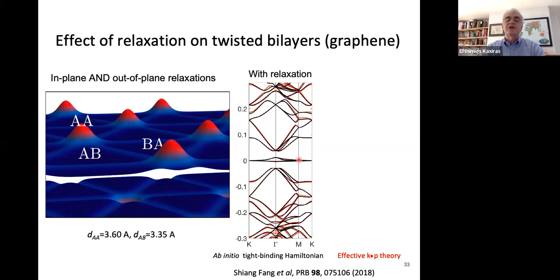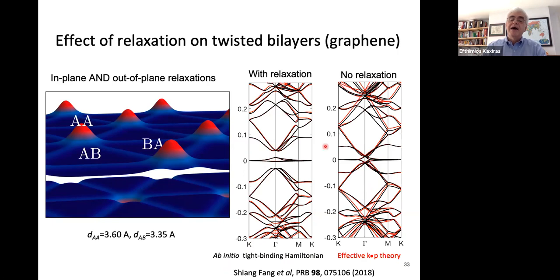So here's the band structure again, and here are the bands associated with this relaxed atomic configuration. The black lines are from our ab initio tight-binding Hamiltonians. The red lines are an effective perturbation theory, which basically captures all the important features. So this is with full relaxation, and it's very realistic, corresponding to the experimental measurements. Without the relaxation, the bands are actually a bit of a mess. No gaps here separating these two bands from the rest, and really very mixed, which is unrealistic.